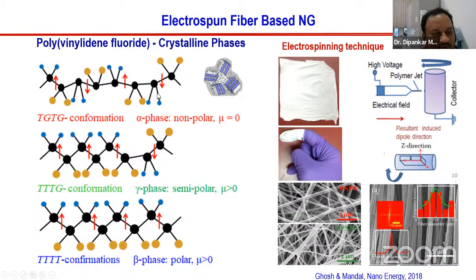Phases means crystalline polymorphs. One is the alpha phase. You see the black dots are carbon, the blue are hydrogen, and this is fluorine. So CH2, CF2. However, they can arrange in different fashions. This is a dipole, let's say, from F minus to H plus. But this is oriented in different directions. This arrow is downward, this arrow is upward, this is downward. So the net polarization is zero. This is called the alpha phase, a trans-gauche phase. So this will not give rise to piezoelectricity.